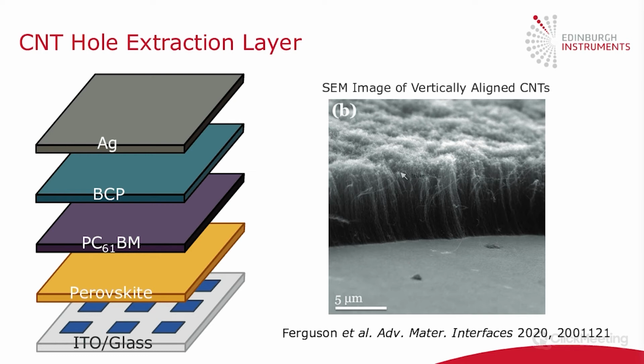Here is a different image so you can see what this looks like. This is taken from the paper, so we were a collaborator on this paper. If you want more details, you can see the paper in Advanced Materials Interfaces. But the idea is that you've got this patterned substrate on the ITO with vertically aligned carbon nanotubes. This is an SEM image just to show what these carbon nanotubes look like. And now I'm going to show how confocal photoluminescence microscopy can be used to characterize the properties of this perovskite carbon nanotube layer.